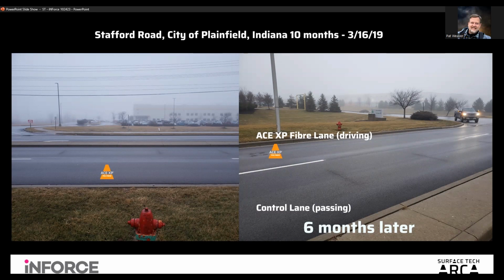This is in Indiana, placed in 2018, which is an arterial roadway, 2-inch overlay on top of old concrete Portland cement pavement. So you can see the control section. This has a polymer modified binder, again, a 76-22, I believe, which is right around a 3% poly load. And then our mixture, basically the same mixture with 1 dose of fiber. In 10 months, you're already starting to see reflective cracking come through. And on our side, nothing.